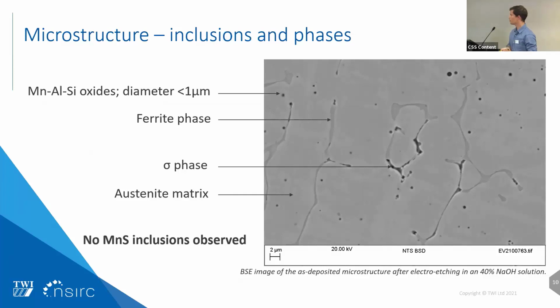Sigma phase is a chromium and molybdenum rich phase, which will be problematic for the corrosion properties, since it can create depletion zones around it in its vicinity. We need the chromium and the molybdenum within the matrix to ensure good corrosion protection.